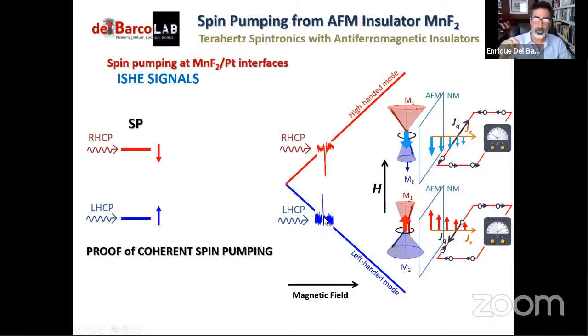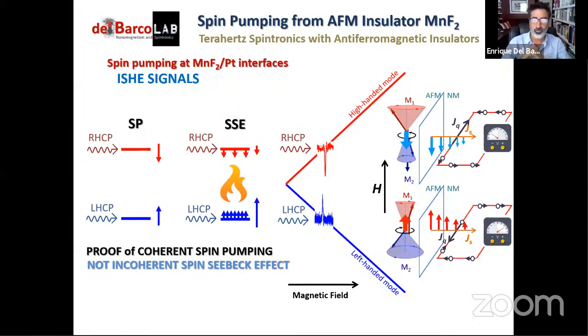And I say this because it is actually very common to observe electric signals out of the inverse spin Hall effect when using microwave radiation because of heating as a result of the spin Seebeck effect. But if this was the case, we would have a different behavior, right? So for example, the spin Seebeck effect works as follows. We heat the system with microwaves, and then we establish a gradient of temperatures across the interface, into the device.